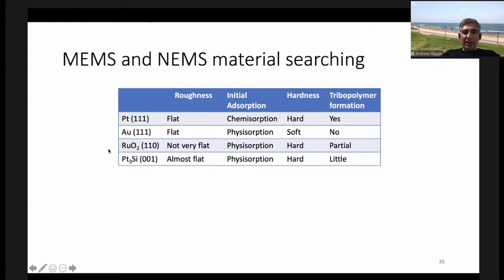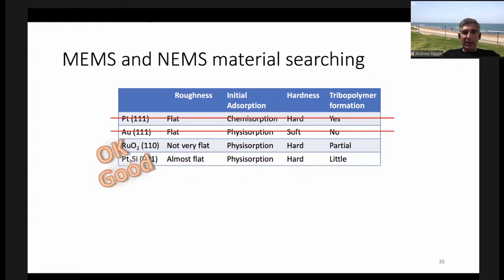And we would say that ruthenium dioxide, because it's not flat, it has a corrugated structure, we think that helps foster this reaction, which in this case we don't want. And so we would rate that ruthenium dioxide might be okay, but a platinum silicide looks like a really good candidate.